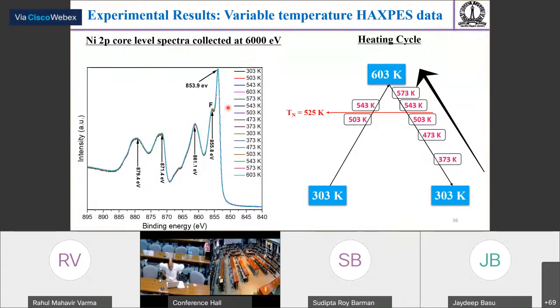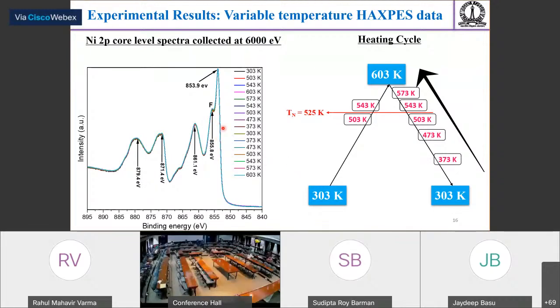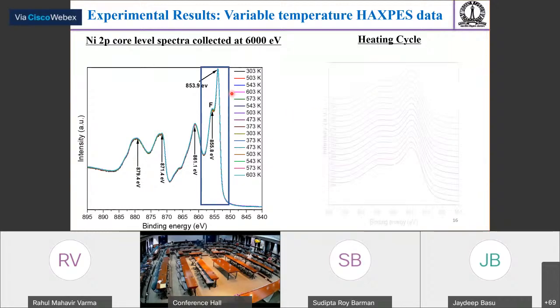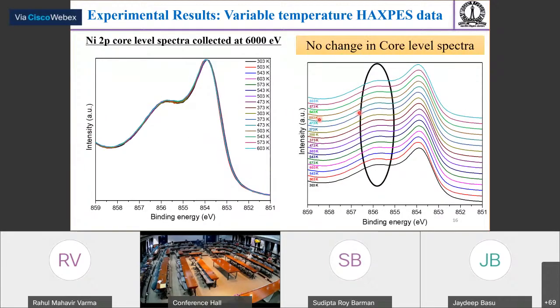This is the nickel 2p core level spectra collected at each of the temperatures during the whole cycle we have performed. And interestingly, we can see all the core level spectra are matching well and are reproducible. So we are focusing on this doublet feature, which is coming due to the non-local screening from the nearest nickel atom. If we zoom into this part and stack all the spectra on top of each other, we clearly see no change in the core level spectra.